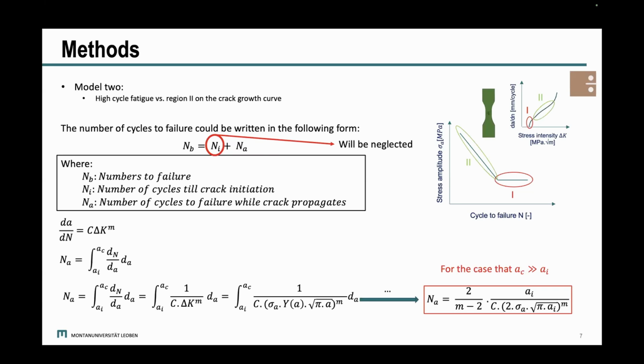By integrating the Paris formula from the initial defect size or initial crack length to the critical crack length, and by considering that the critical crack length is reasonably greater than the initial crack length, we can use this formula to find the number of cycles from the startup loading to failure.